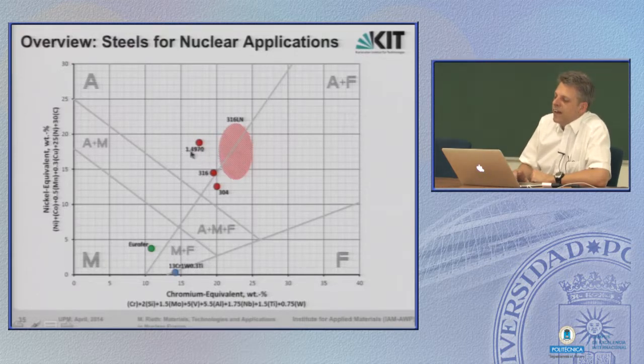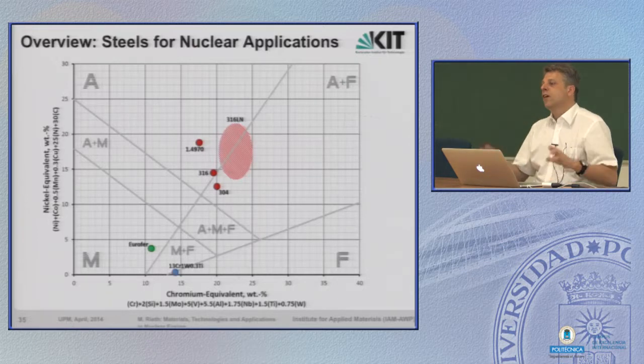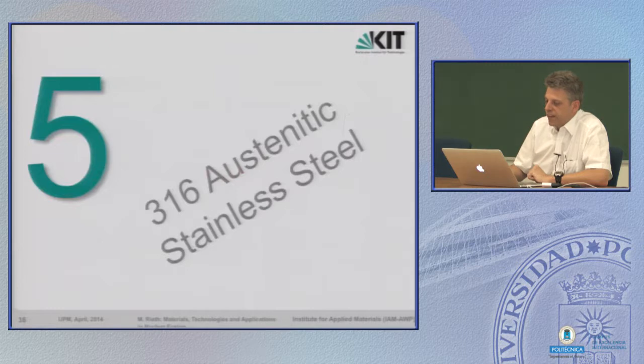For example, for a cladding material for fission reactors, also austenitic steels, you end up here fully in the middle of the austenitic phase. Eurofer and its composition, you end up here in the diagram. It shows you that it's martensitic steel. And these ferritic ODS steels with 13% and more chromium, you would end up here along that line in the ferritic phase. This is how you can produce different types of steels depending on the alloying.